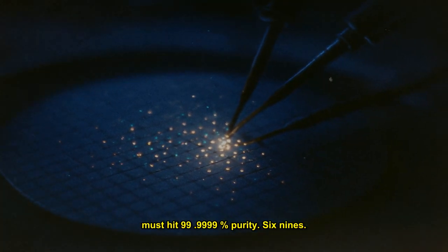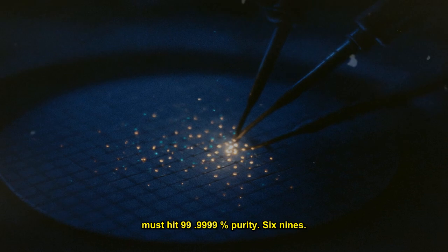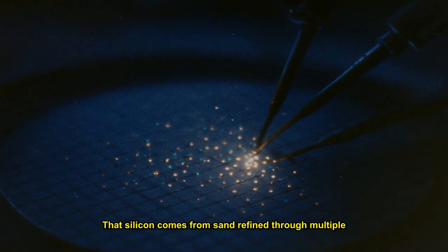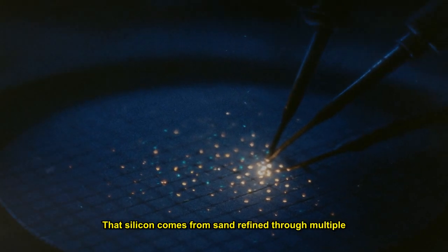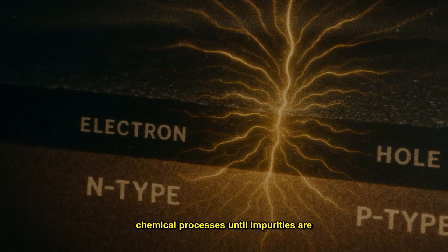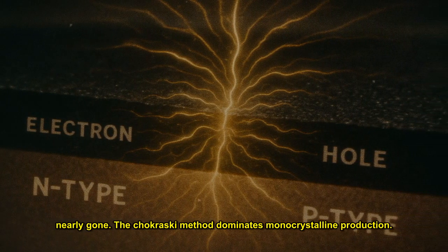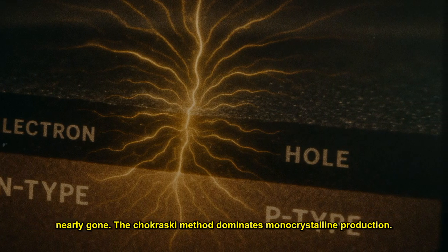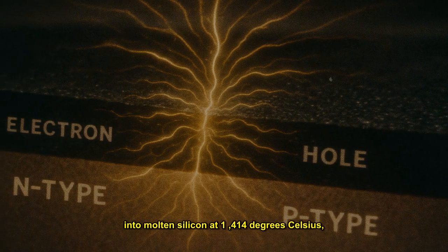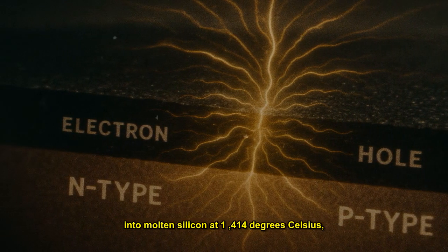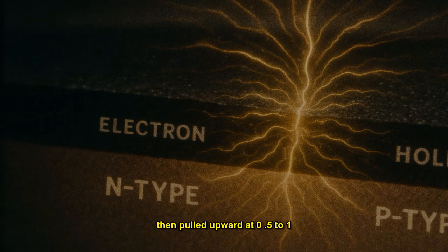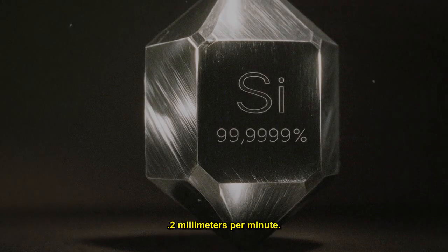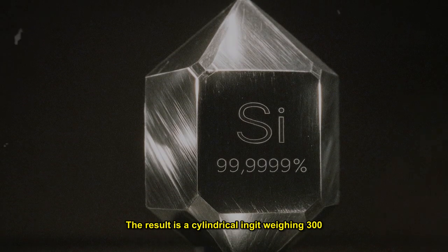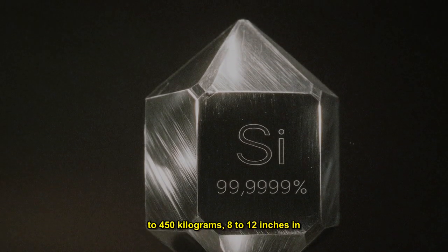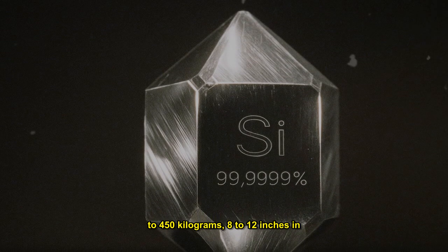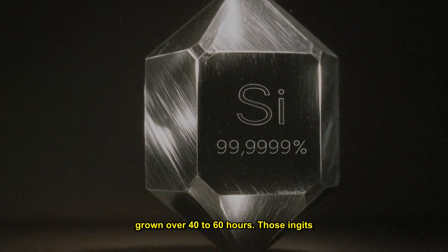Solar-grade silicon must hit 99.9999% purity, 6 nines. That silicon comes from sand, refined through multiple chemical processes until impurities are nearly gone. The Czochralski method dominates monocrystalline production. A seed crystal gets dipped into molten silicon at 1,414 degrees Celsius, then pulled upward at 0.5 to 1.2 millimeters per minute. The result is a cylindrical ingot weighing 300 to 450 kilograms, 8 to 12 inches in diameter, grown over 40 to 60 hours.